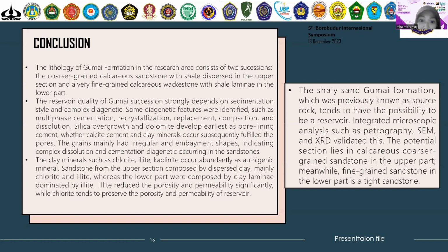Silica overgrowth and dolomite developed earliest as pore lining cement, whereas calcite cement and clay minerals occurred subsequently, filling the pores. The grains mainly had irregular and embayment shapes, indicating complex dissolution and cementation diagenesis occurring in the sandstones. The clay minerals such as chlorite, illite, kaolinite occur abundantly as authigenic minerals. Sandstone from the upper section is composed by dispersed clay, mainly chlorite and illite, whereas the lower part is composed by clay laminae dominated by illite. Illite reduced the porosity and permeability significantly, while chlorite tends to preserve the porosity and permeability of the reservoir.